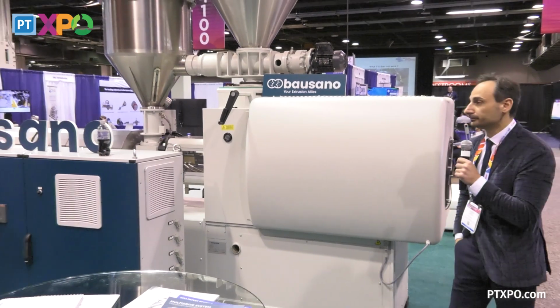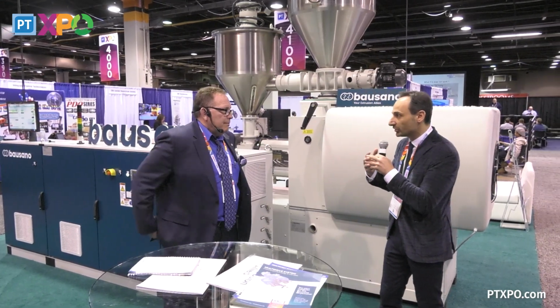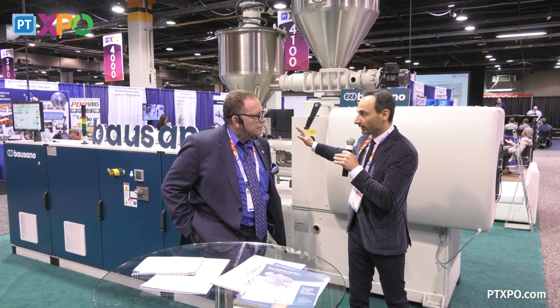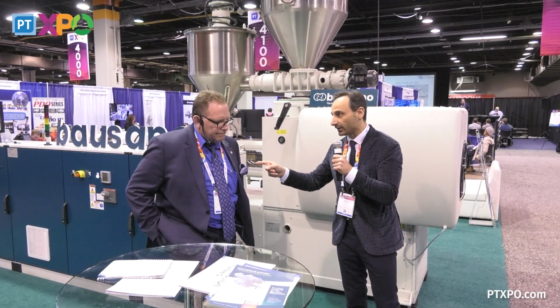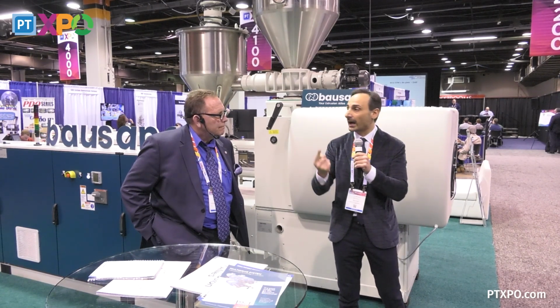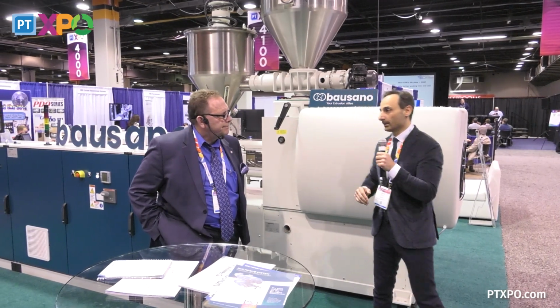Do you know why, JR? Because you know that in PVC, we need to reach the gelation point. How can we reach the gelation point? By the mechanical shearing of the material and by the heating system. With the traditional extrusion line, you reach the gelation point mostly by the heating of the barrel. With the multi-drive system, we can have a high torque. Why? Because we have 4 motors, and each motor is dedicated to 1 part of the gearbox. For this reason, we can handle a high torque. This high torque allows us to reach the gelation by the mechanical shearing and not just by the heating of the barrel.